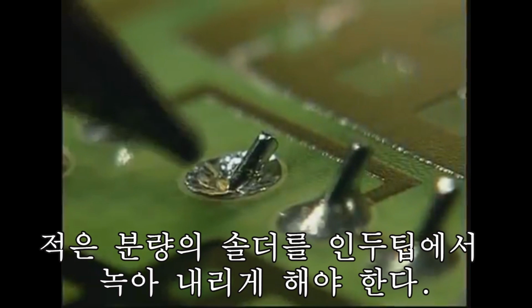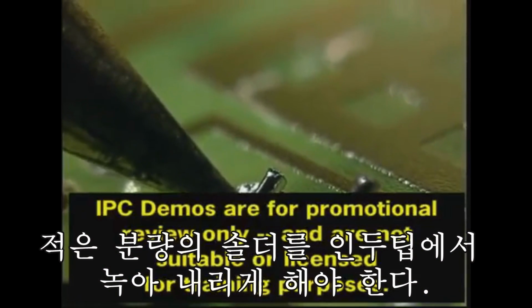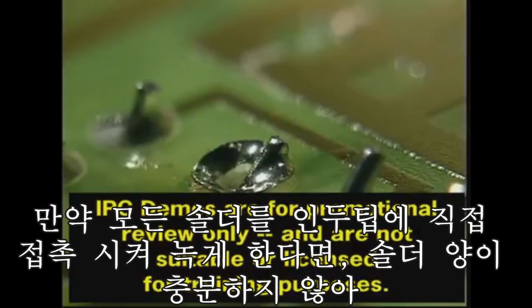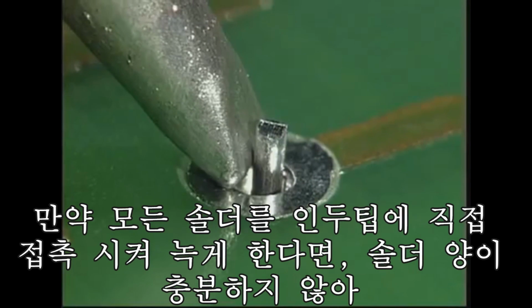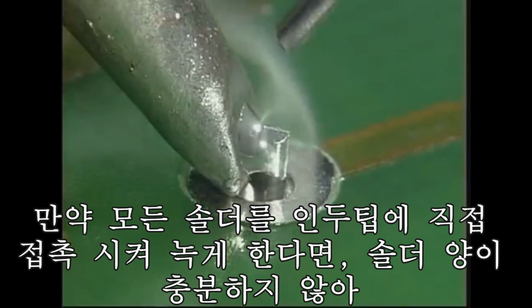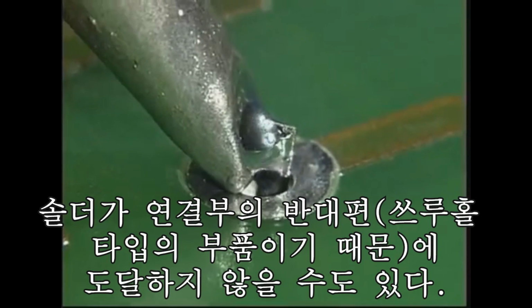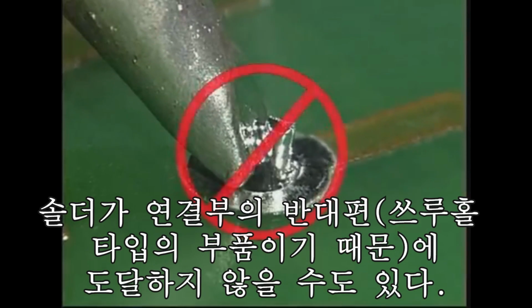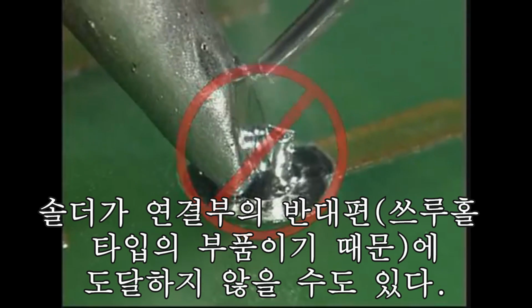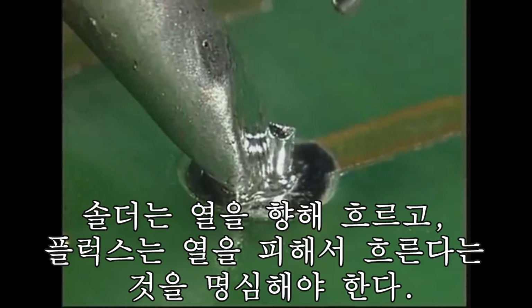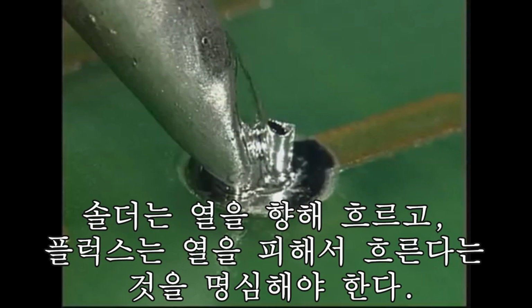The tip should lightly contact both parts to be soldered. Pressing down firmly with the tip will not transfer the heat faster, but it may damage the land or the base material. Only a small amount of solder should be melted against the tip of the iron. If you melt all the solder by touching it directly to the tip, you may not get enough solder to flow onto the other side of the connection. Remember that solder flows toward the heat. Flux flows away.